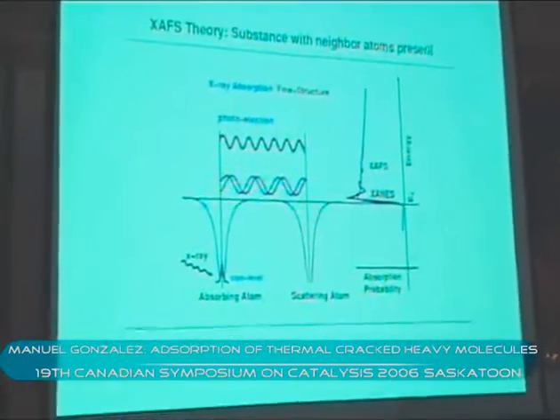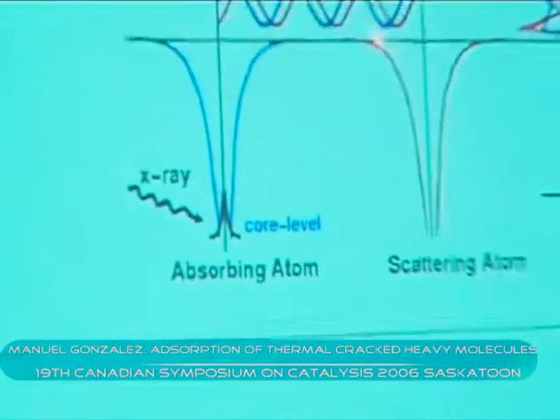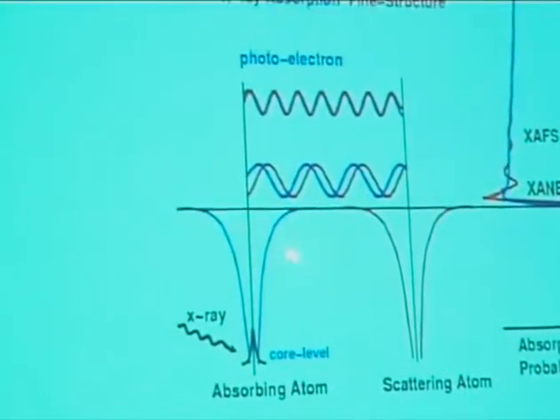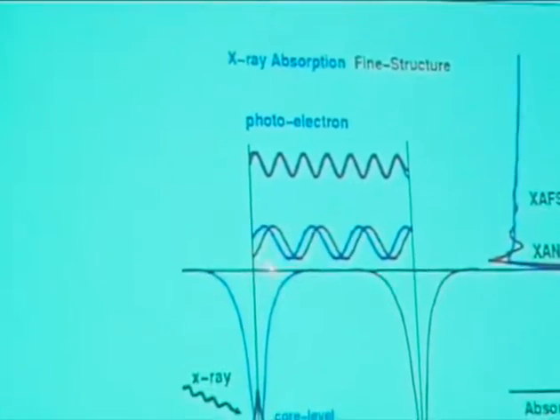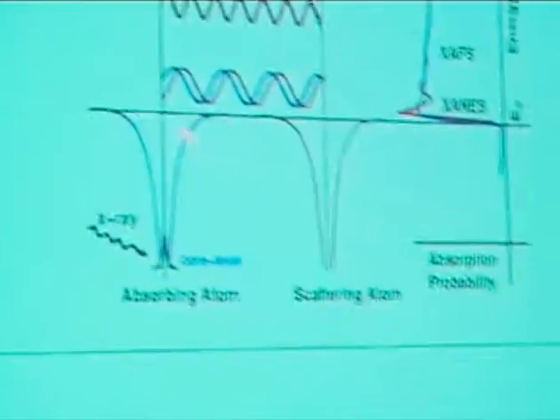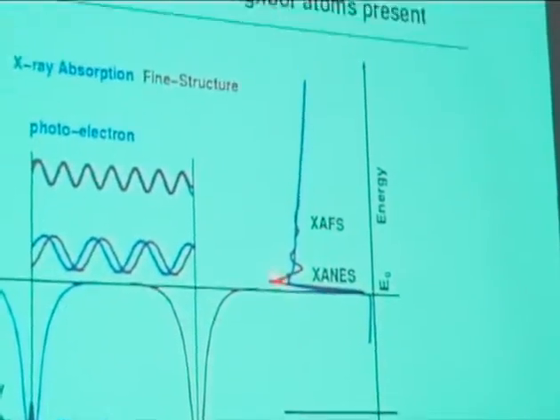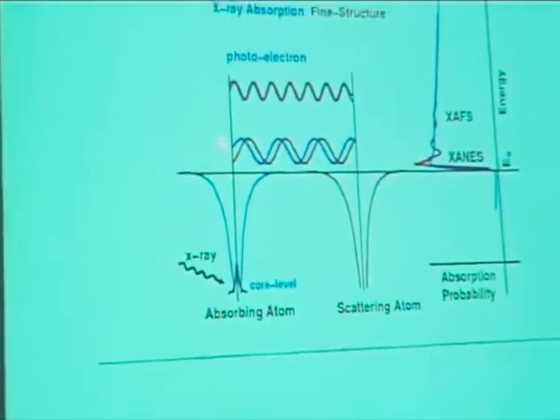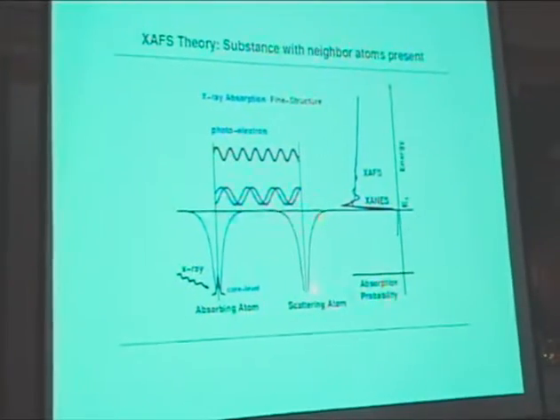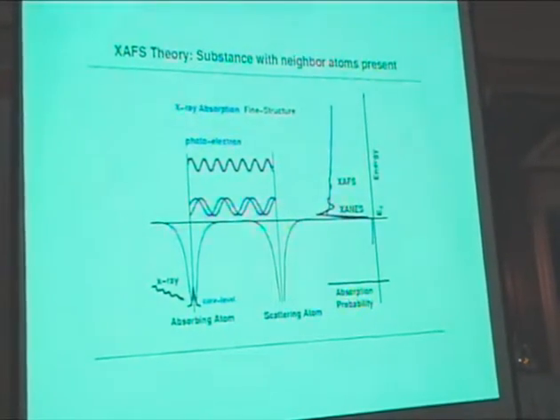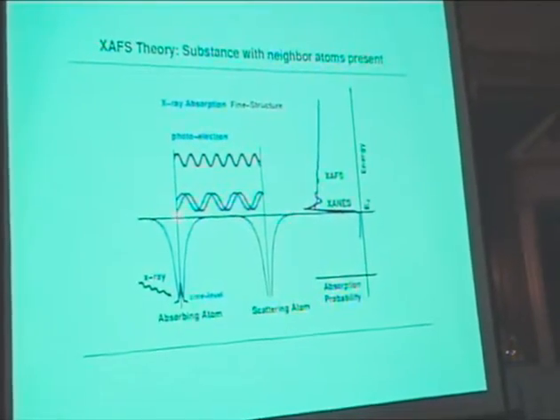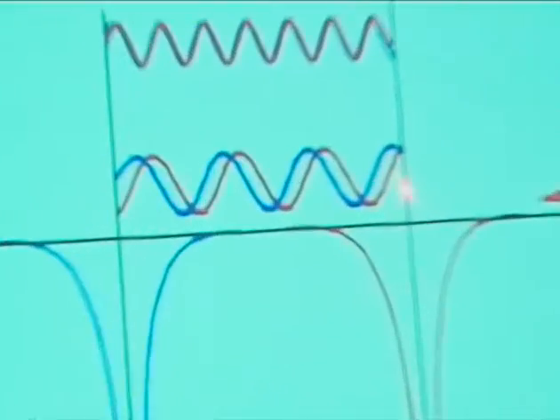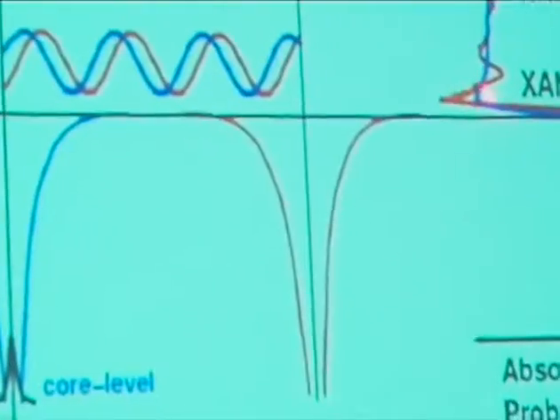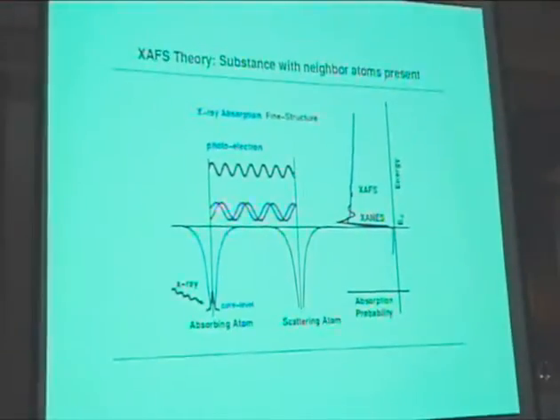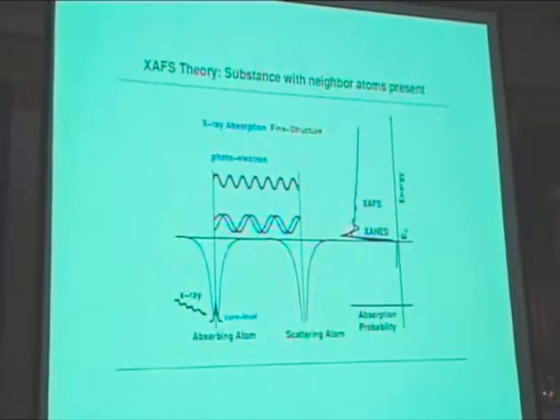However, if there are atoms surrounding this atom, then in the first place you still have what I showed you in the picture before: the majority of electrons will go out and will not see the neighboring atoms because space is very empty there. So you still have a sort of background as before, but an electron which is going in the direction of a neighboring atom can be scattered by this neighboring atom. It is as if you're making a standing wave between the point where the electron is starting and where the electron is scattered by the backscattering atom. And because of this standing wave, you suddenly get an increase in the absorption coefficient of the original X-ray photon. And then you see a peak in the spectrum.